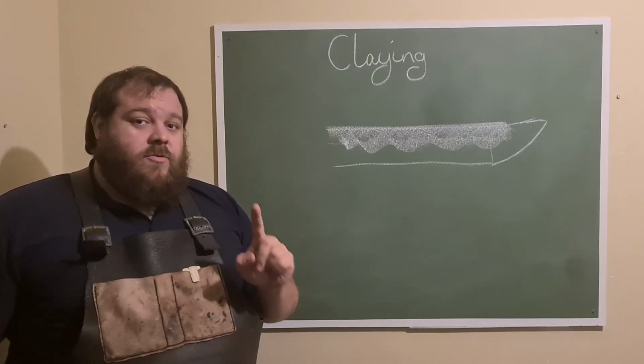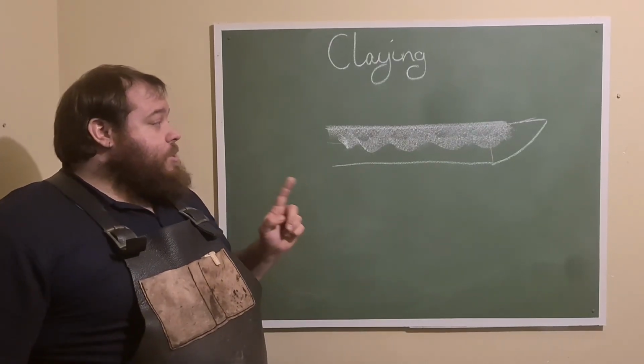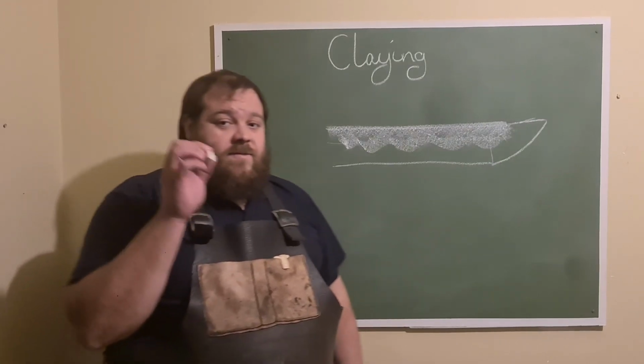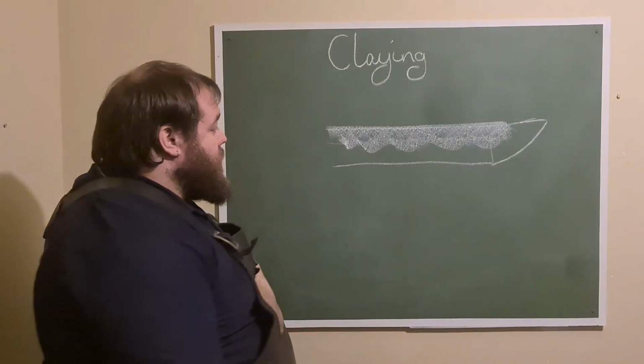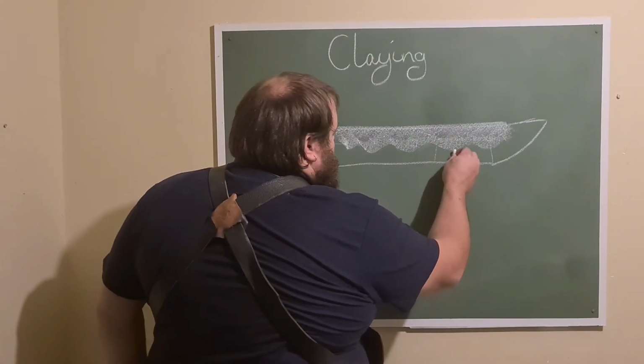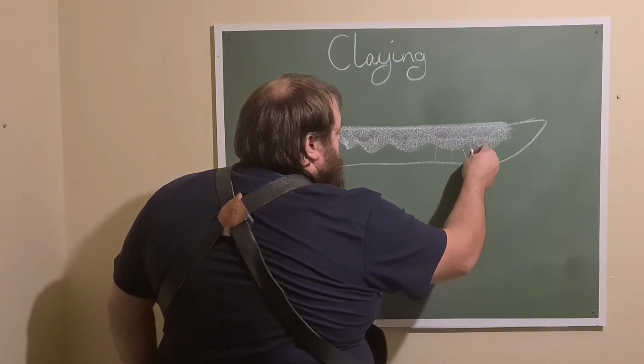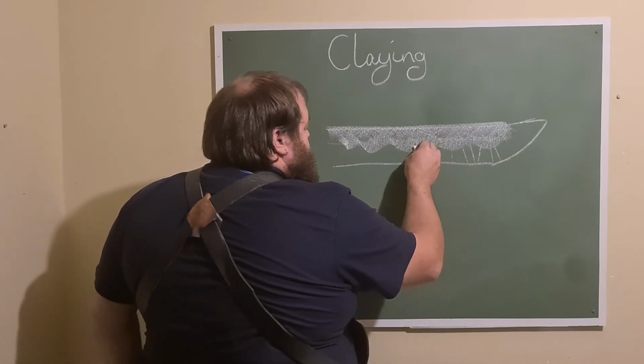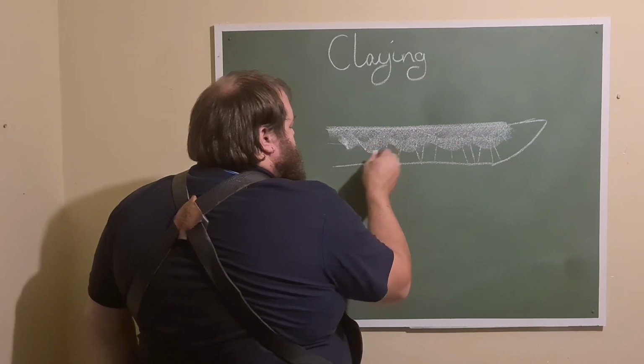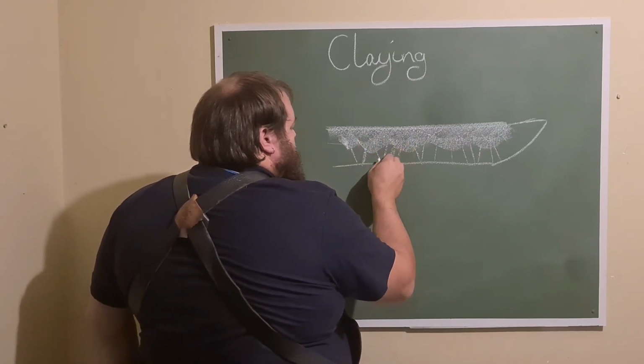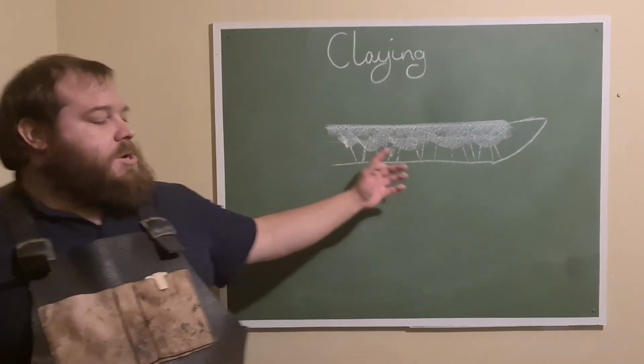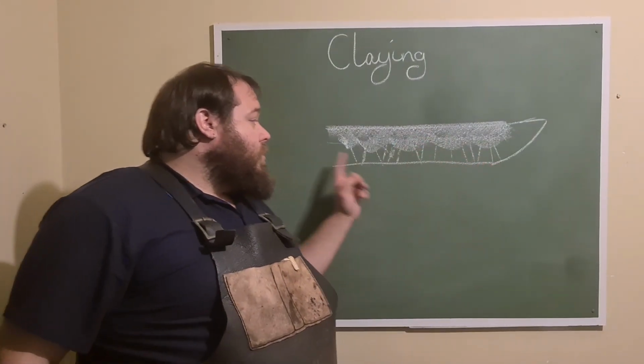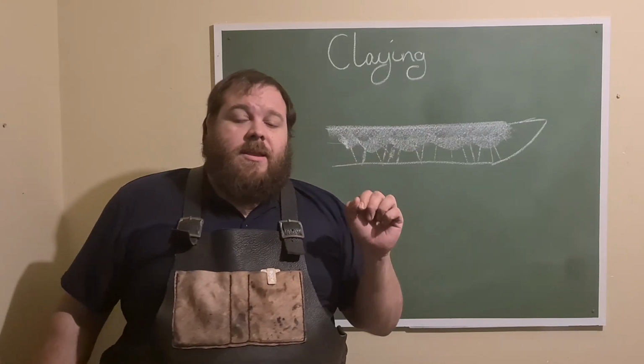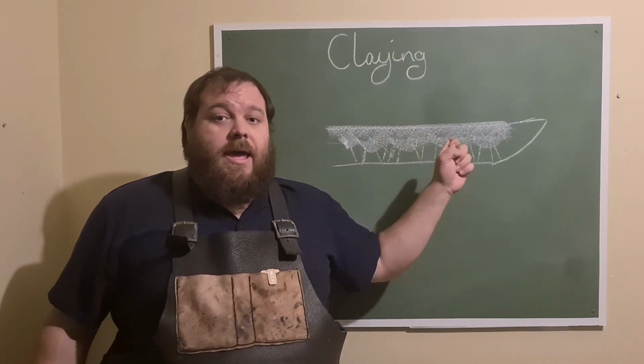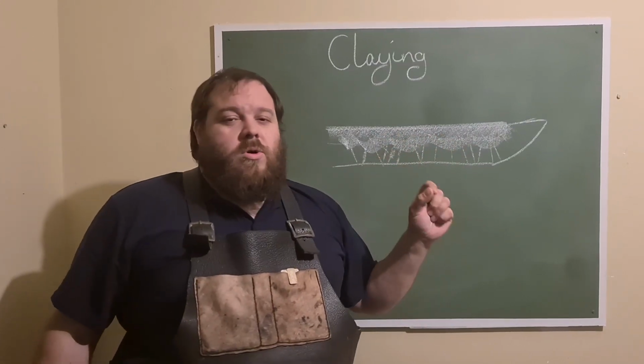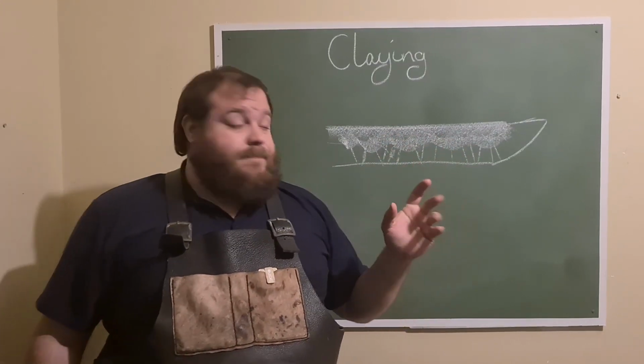The same is not true of ashi. When applying ashi lines, you actually apply a very thin line of clay, and I'm going to use my chalk to represent it, away from the edge. You can apply ashi in any way you like. You can use dots, you can use lines, but in most cases it does not have to be measured, because when the ashi are applied, and they go almost to the edge, you don't have to go all the way to the edge, but they are very, very thin, and they're not the same thickness as your main clay. They are normally only a quarter the thickness of your blade width, if not less.